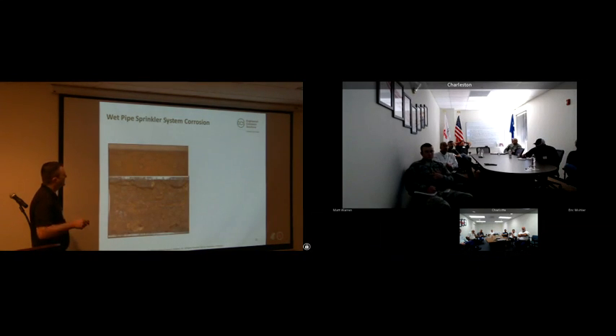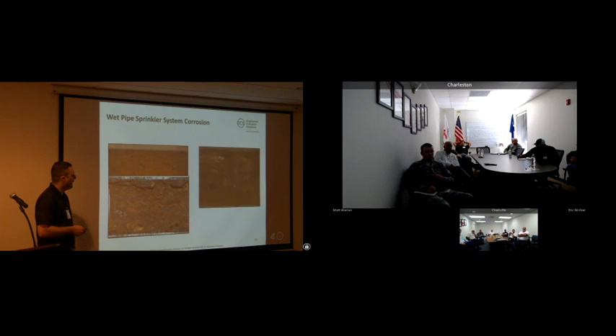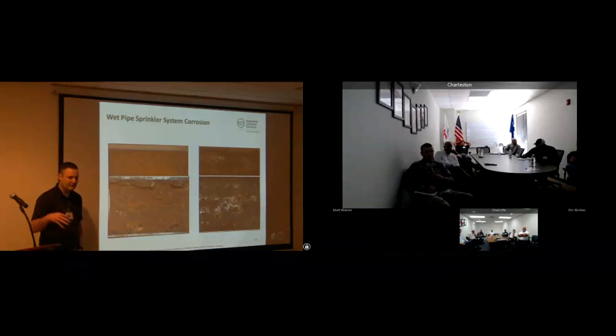So when we get pipe samples, they come into us, we evaluate them for corrosion. One of the things we look at, so we'll take the pipe, we'll cut it in half, we'll look at the corrosion buildup in the pipe, which is what these pictures are. We'll actually media blast that pipe so we can get down to the metal, so we can see the metal loss signature, and we're going to look at those pictures here in a second. That's how we can tell you if it's MIC, if it's oxygen corrosion, acid corrosion, or whatever type of corrosion it is.